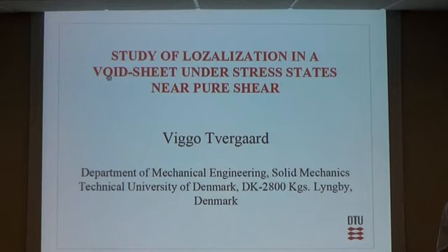Here's maybe the last slide I should show, because the other slides just show that it does the same. But this is interesting in that the unit cells I have shown so far had an aspect ratio of 2. If you make the aspect ratio 4, that means it is 4 times as high as it is wide, then you should find exactly the same result, because the whole idea is that the boundary conditions are against the solid at infinity, and this really shows that they are nearly the same.